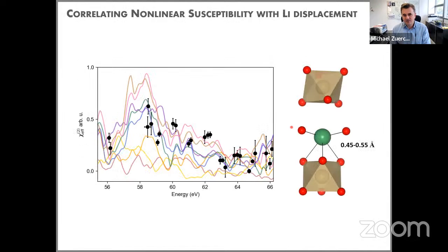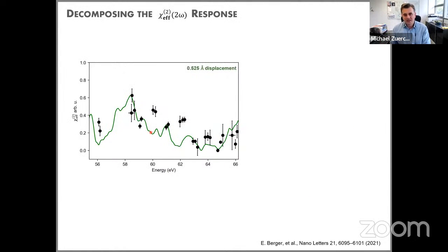But now we have to think a little bit more about what we actually measure here. I keep writing Chi2 effective, and I kept mentioning before this is actually a tensor. So this is something that links different directions in the crystal with different polarization directions, and different polarizations of the electric field. So there is something about directionality in here. And what we measure is something effective, because really at each photon energy, it's a scalar we extract. And so, just showing now the best fit to our data, let's think about what this really means.